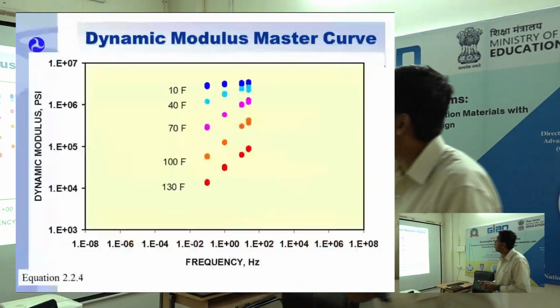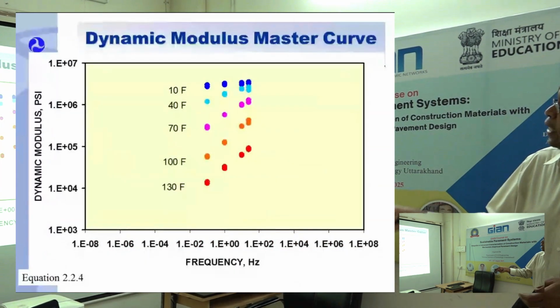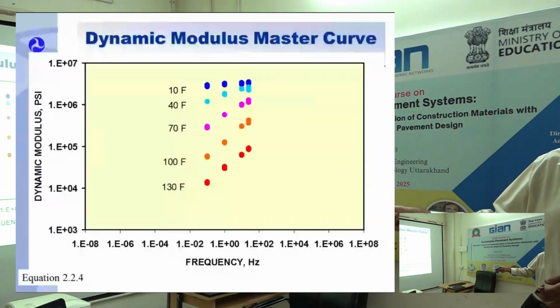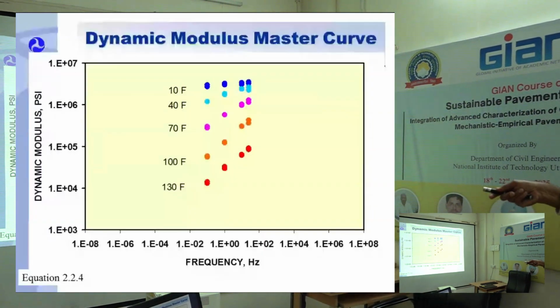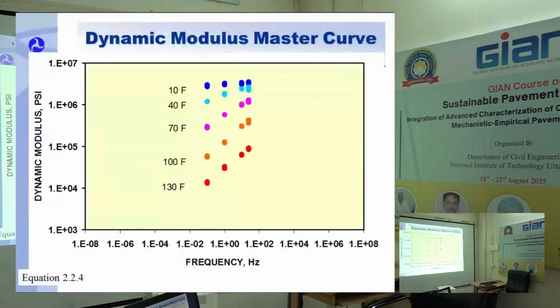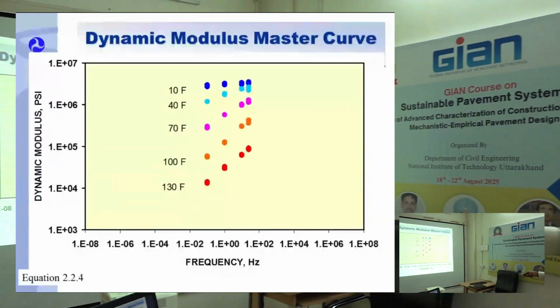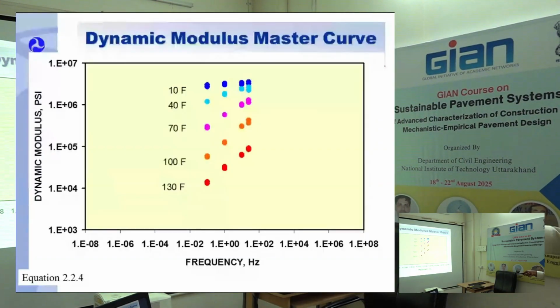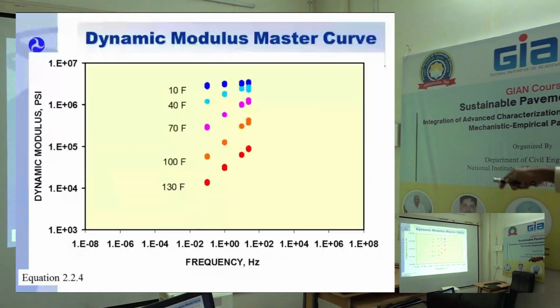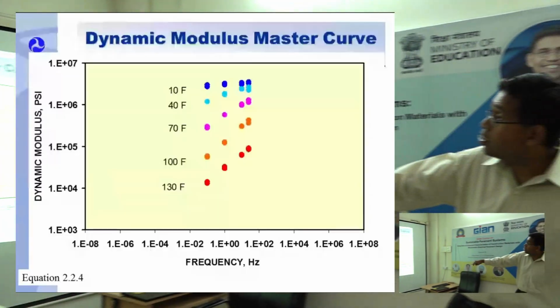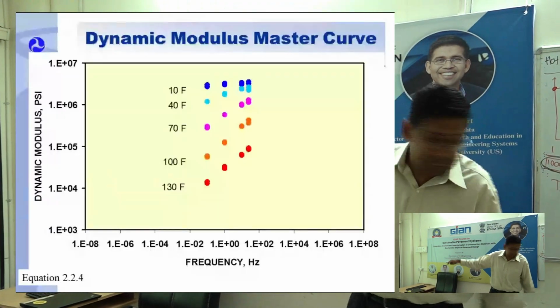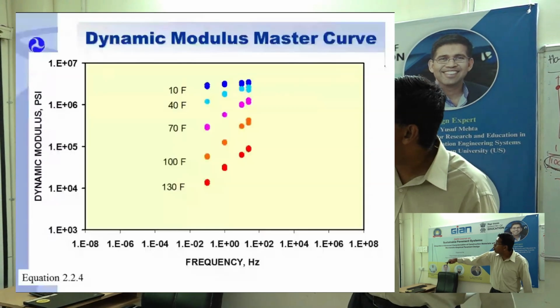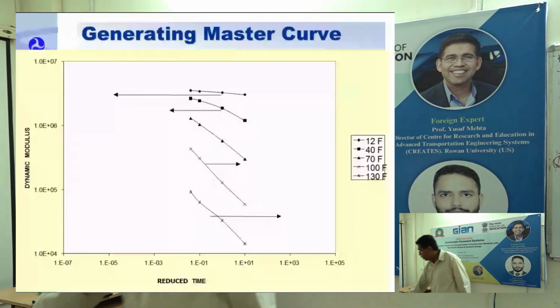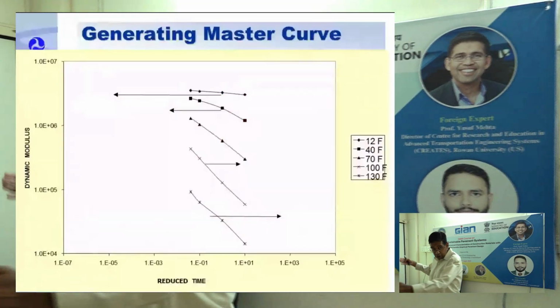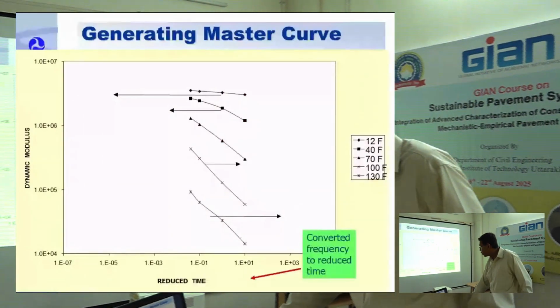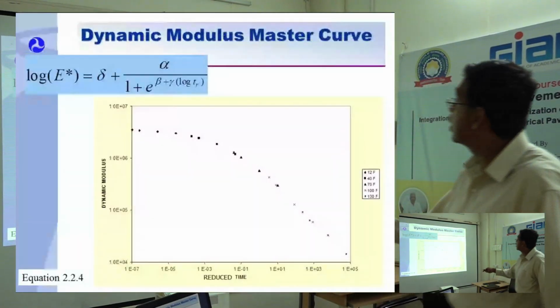Right here, this is a very good graph. This is actual data at 10, 40, 70, 100, 130 Fahrenheit. So as I make it warmer, my dynamic modulus drops because asphalt flows. If frequency goes up, if I load it faster, my modulus goes up. So from 0.1 Hertz, I think that's what I said before, 10 seconds to the same amount is right here. And then you shift horizontally and vertically, convert frequency to time, and you get this equation.